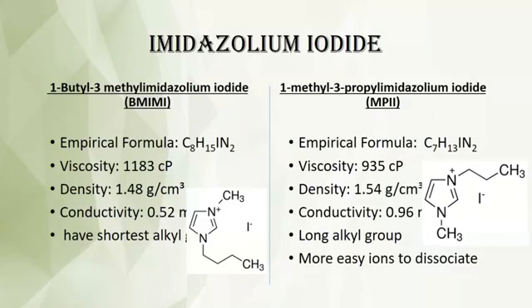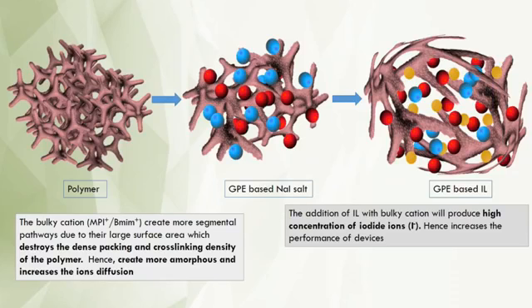In our lab, we also managed to synthesize a few iodide-based ionic liquids, such as 1-butyl 3-methyl-imidazolium iodide and 1-methyl 3-propyl imidazolium iodide. So these ionic liquids show excellent properties when we use them in the electrochemical devices. Normally we can see for ionic liquid, the bulky cation can create more segmental pathways which destroy the dense packing and cross-linking density of the polymer. So they can create more amorphous regions and increase the ion diffusion.